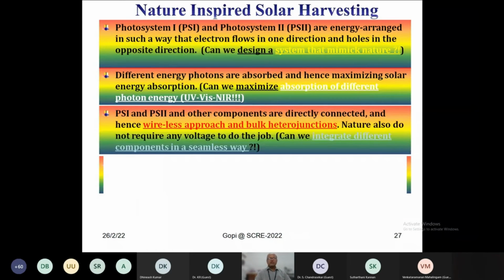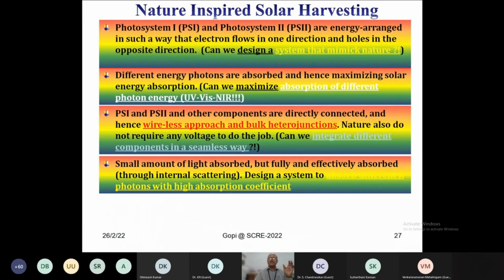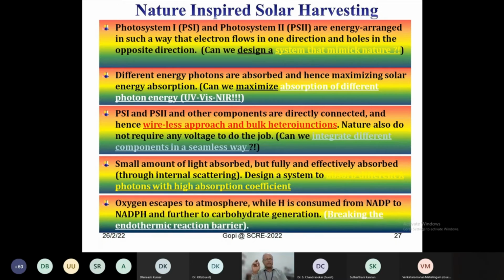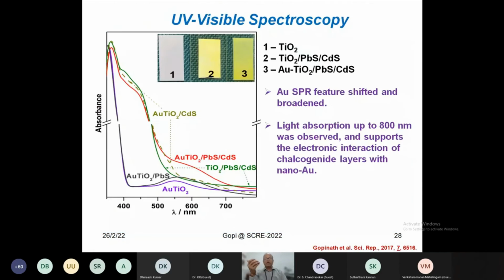This also leads to wireless heterojunctions, because cadmium sulfide directly deposits on the titanium dioxide layer and forms a very high quality heterojunction. You don't need any wire. Another thing is that since it is deposited as quantum dots, light absorption becomes no problem. This is another clue we got from nature. In natural photosynthesis, oxygen escapes to the atmosphere. Here, to overcome the thermodynamic barrier, we use a sacrificial agent. That way we are able to simulate nature from the clues we got.